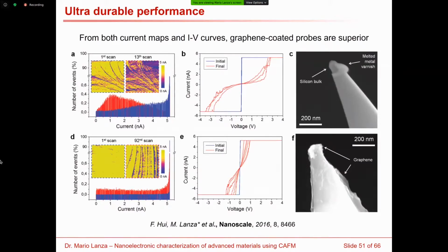Of course, if you analyze the tip coated with graphene using SEM after 92 scans, you are going to see that there are some particles attached, but this is something normal in all AFM tips that are used for 92 scans. The important thing is that the conductivity is maintained.